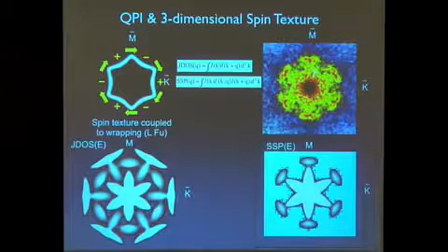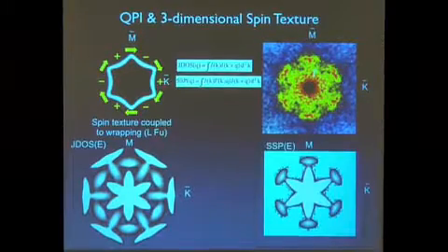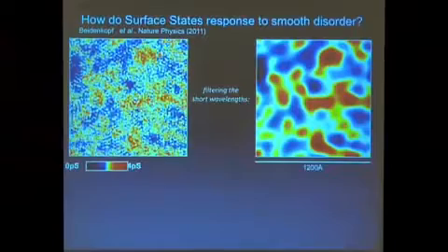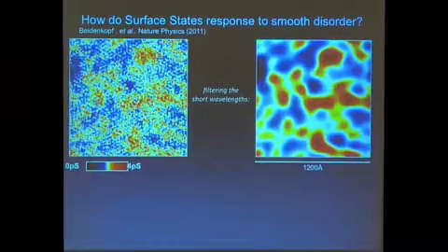So here's a situation in which you have a 3-dimensional spin texture, if you like, that's really restricting the possible ways you can scatter in this compound. Now this goes to your question. I won't spend a whole lot of time on it. What I've been focusing on is scattering from basically short-range potentials. And of course, there's no backscattering, so people might think, oh, these states can basically go through material without any kind of electrical resistance or any impediment but impurity.